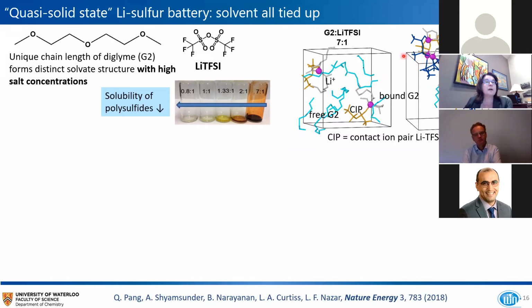And this is shown by computation carried out at the Argonne National Labs by Larry Curtis and his associate, Badri Narayan, in which they compared, using ab initio molecular dynamics modeling, a very high electrolyte or low salt ratio to a high salt ratio condition. So in other words, lots of electrolyte, very, very dilute condition, to a very high salt condition. That'd be the easiest way to describe it.